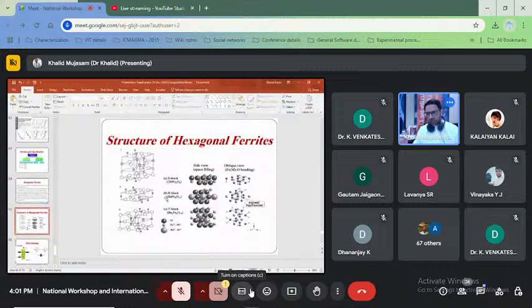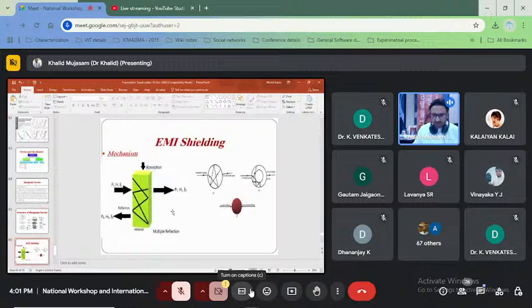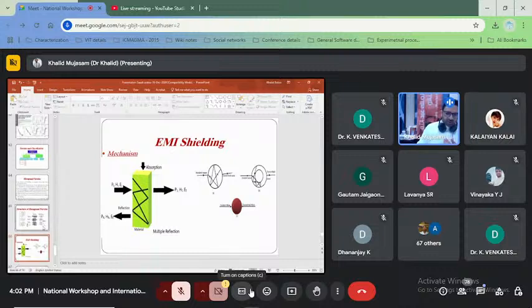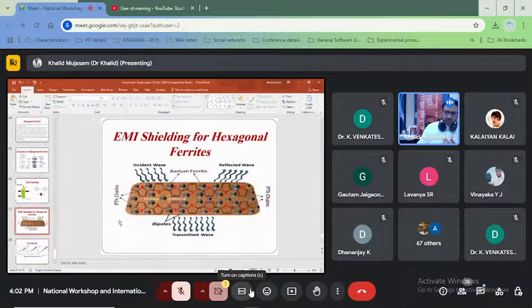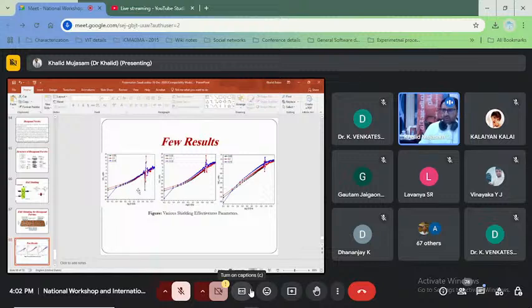So what is actually happening in these? I may not go into the details of this, so let's go to the mechanism. We have three parts here: absorption and reflection. This is the material. Here you can see the absorption happening inside the material, and here is the direct incident wave and the reflected one. It is possible that you can have multiple reflections. So you can use ferrite materials for electromagnetic shielding, and in that case you have to design your material with better permeability losses and permittivity losses, and a few results can be seen here, which we have earlier published.